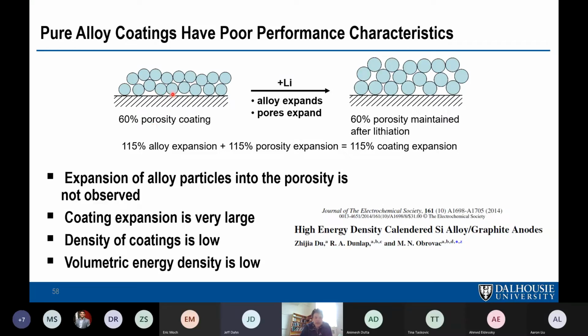If you calender an alloy, they're irregularly shaped particles and they can't slide against each other. And the only way to get the porosity lower is to calender it under high pressure enough to break the particles and cause fracture. And then you can start lowering the porosity. In a lithium cell, those kinds of pressures are never reached. So when this thing expands, it expands basically unrestricted. The separator will crush, the current collector will tear, the whole cell can will bulge before any compaction or lowering